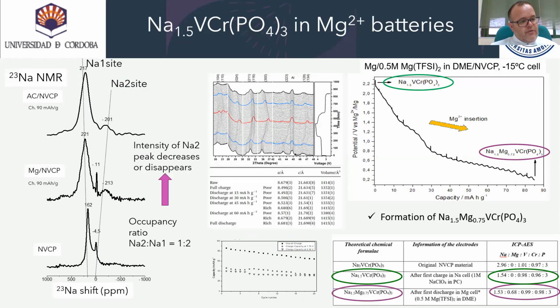The 23 sodium NMR spectra is shown here. The spectrum of the original NVCP sample exhibits two main resonances at -4.5 and 162 ppm. They can be assigned to the partially filled sodium 2 sites and the fully occupied sodium 1 site, respectively. The occupancy ratio is sodium 2 to sodium 1, 1 to 2 in the Nasicon structure. When removing 1.5 sodiums, the intensity of the sodium 2 peaks decreases or even disappears. The sodium 1 peak broadens and shifts.